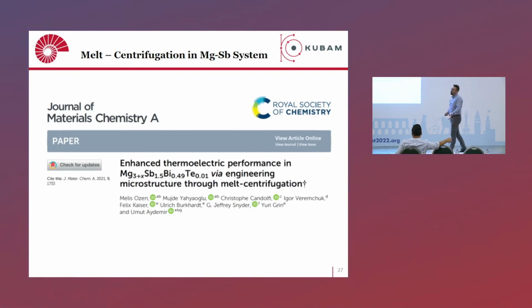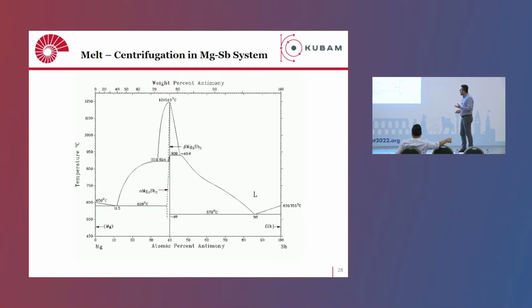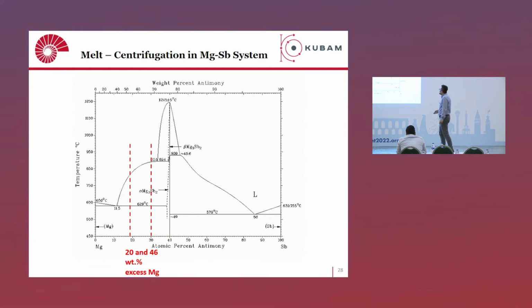features. So we thought, okay, why not apply this to magnesium antimonide? Why? Because the nature is similar. Here you can see this is magnesium 3 antimony 2. Here we have magnesium, and between magnesium and magnesium 3 antimony 2, we see also such a eutectic temperature here. So we just went a little bit higher than 650, maybe 750, by adding excess magnesium and applied this technique. So we added 20 and 46 weight percent excess magnesium, and then did some research to see the effect of it. So this is done in situ and ex situ addition.